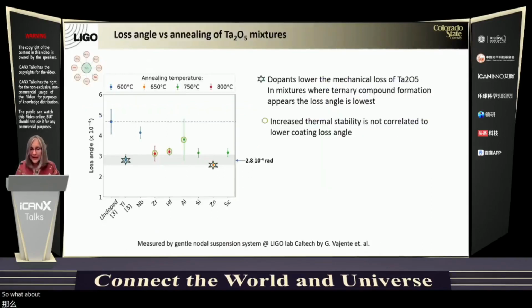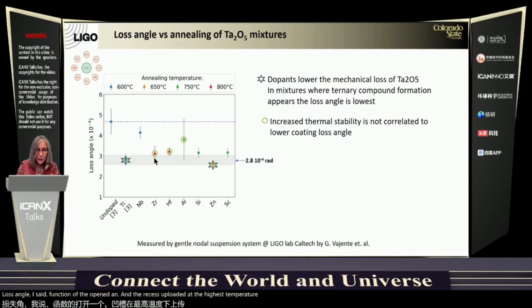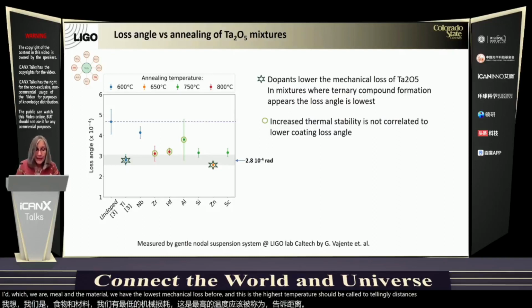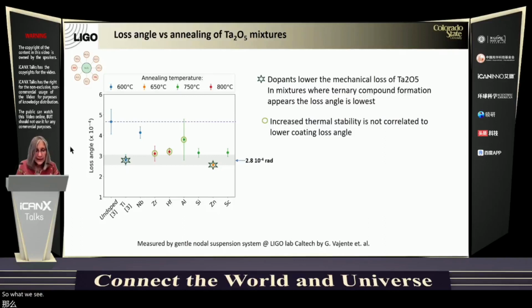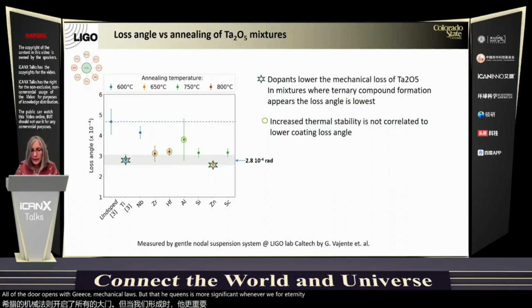So what about mechanical loss? Well, again, this plot shows loss angle as a function of dopant, and the results are plotted at the highest temperature at which we anneal, where the material will have the lowest mechanical loss, and this is the highest temperature before crystallization. So what we see is that all of the dopants decrease mechanical loss, but the decrease is most significant whenever we form a ternary compound.